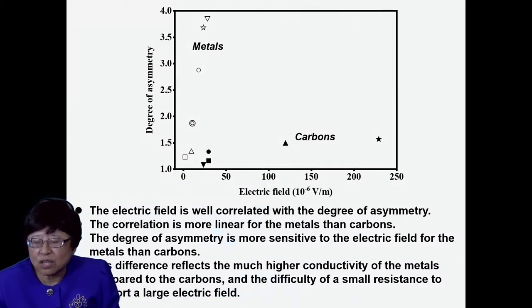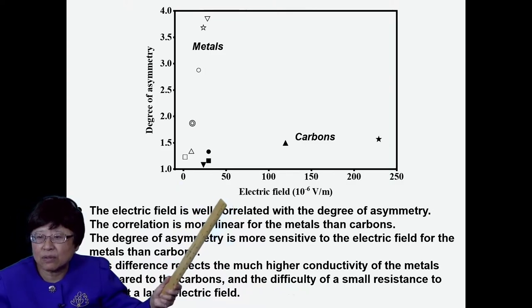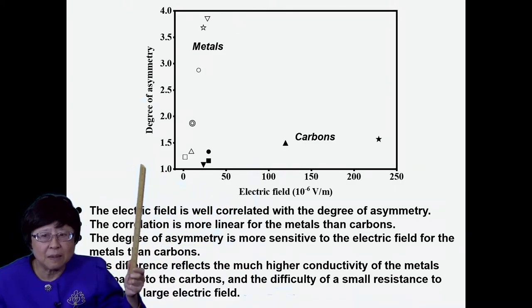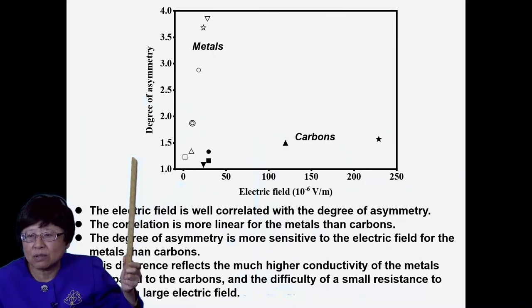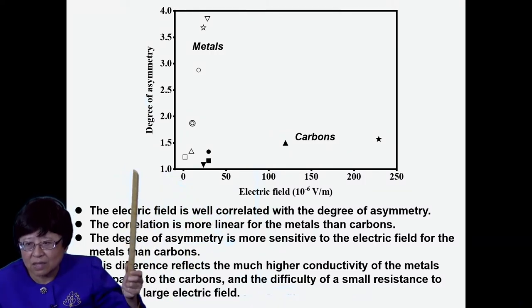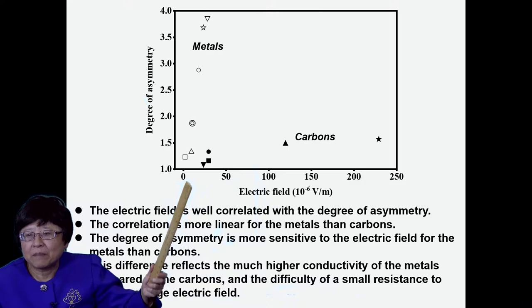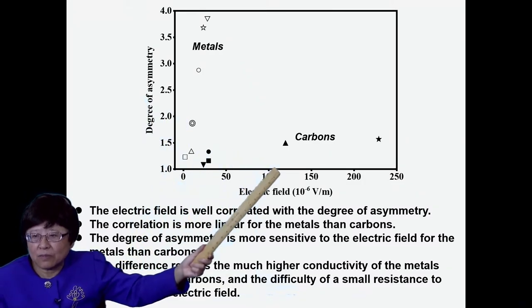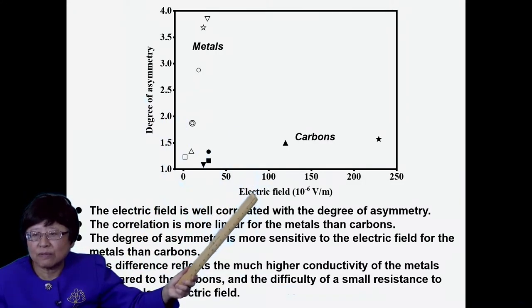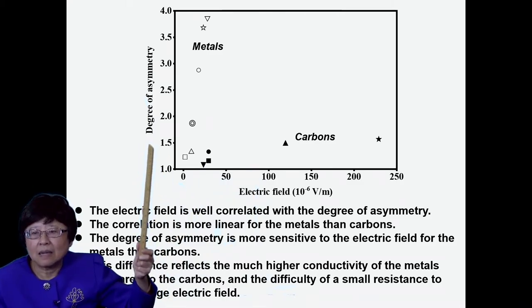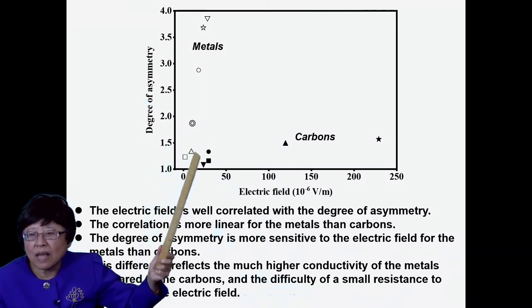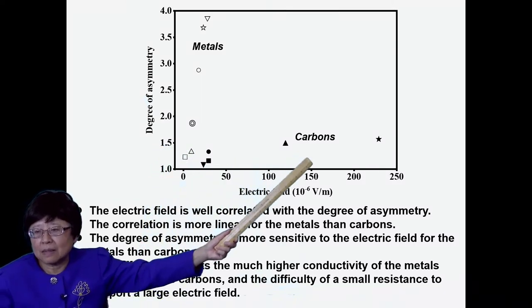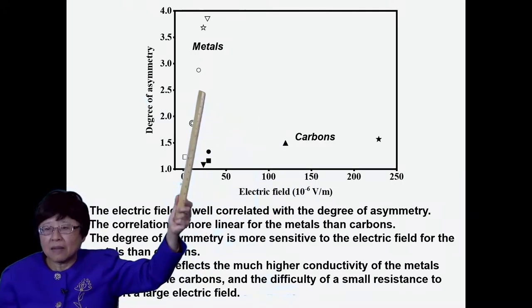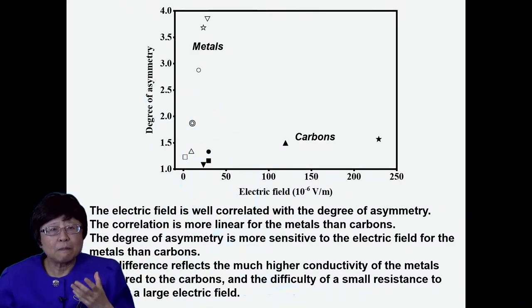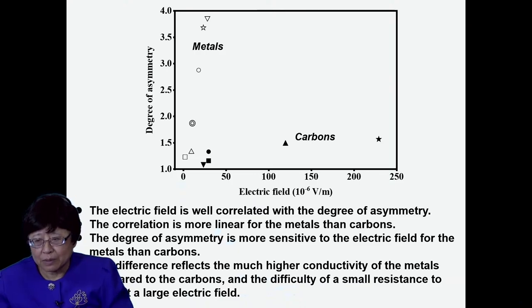This shows the correlation between the electric field in the electret with the degree of asymmetry in that DC polarization curve. And note that they correlate, for the metals as well as for the carbons. The higher the electric field, the higher the asymmetry in that DC polarization. Note that the electric field gets much higher for the carbons than the metals because carbons have much higher resistivity than metals.